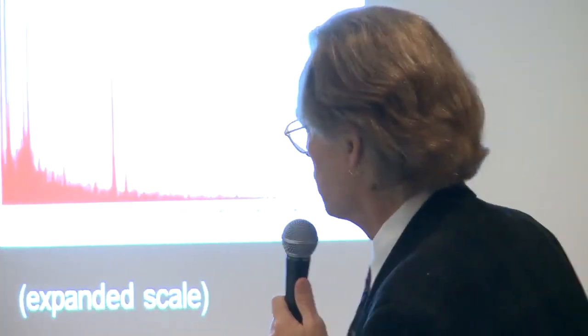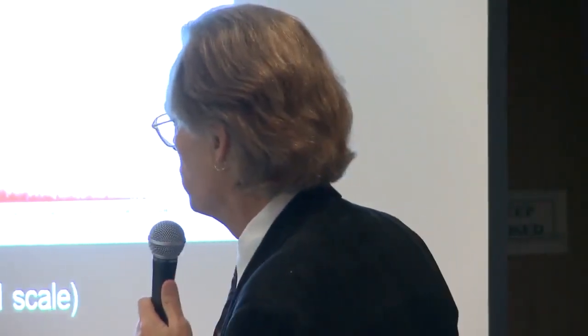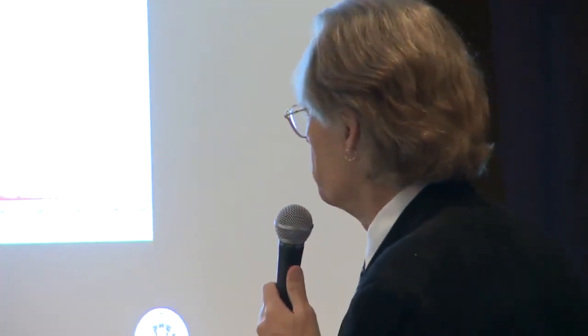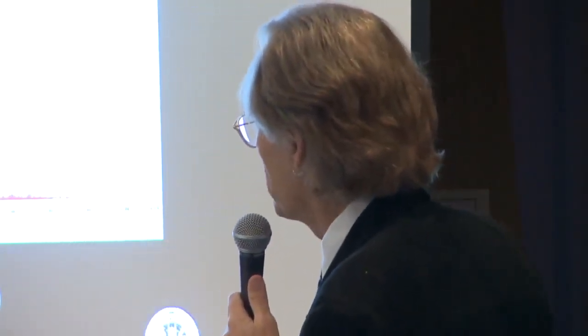I go back to a picture I showed you a couple of minutes ago of the energy dispersive spectroscopy from the red layer here. And here we have blown up the area where you should expect chromium. You can see a little chromium here. We just cannot see zinc. And when you blow up the vertical scale, of course, the regular peaks go completely off the roof. So the signal from chromium is at the level of the noise. It means there's nothing in there. And we can't even see zinc. So the conclusion here is that the red-gray chips cannot be the primer paint because we do not see zinc chromate.